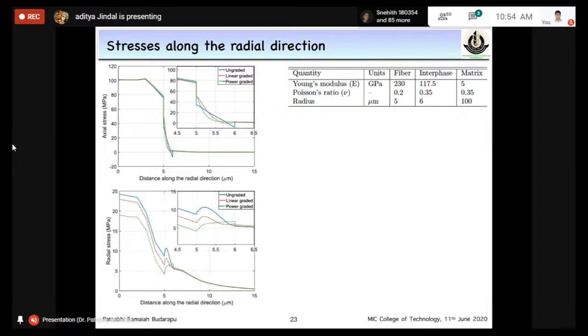This is because the load transfer mechanics happen in the interface, which is clearly shown there. The picture on top indicates the axial stress, and obviously it should be maximum around the fiber surface and minimum at the matrix surface. The trend is exactly as predicted.